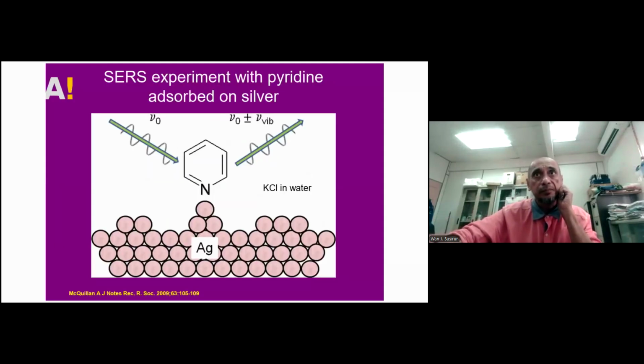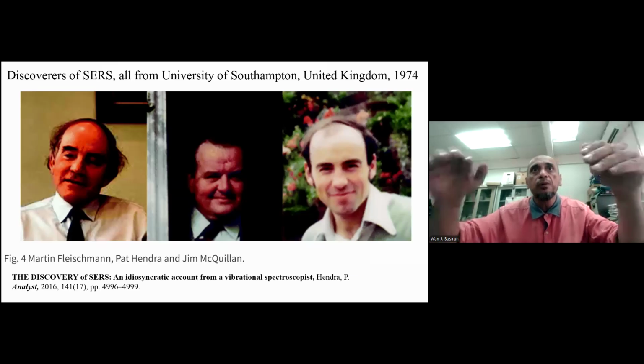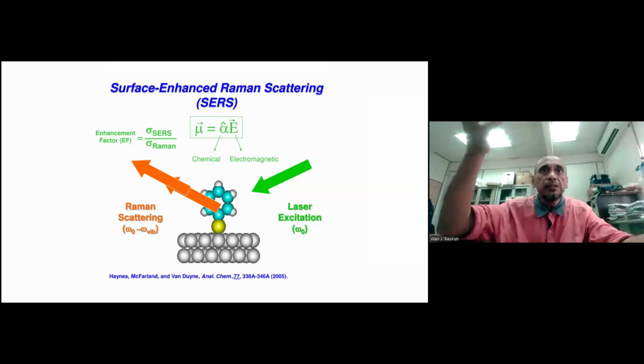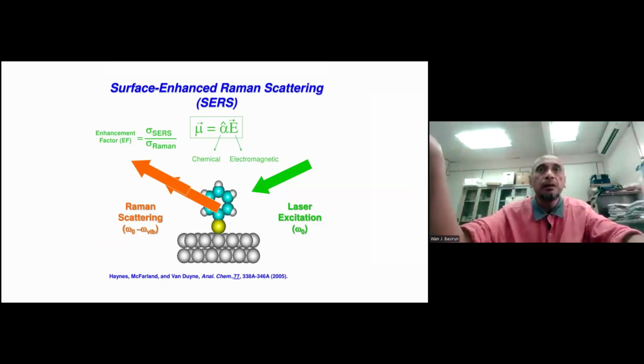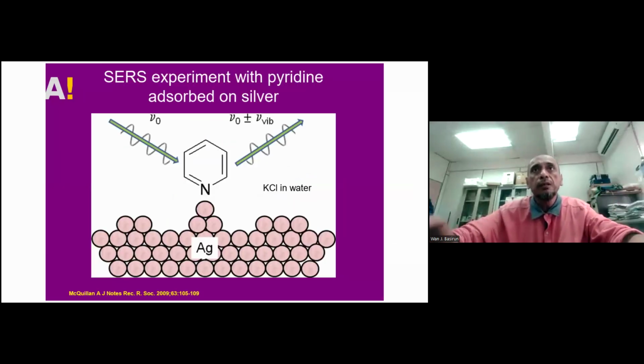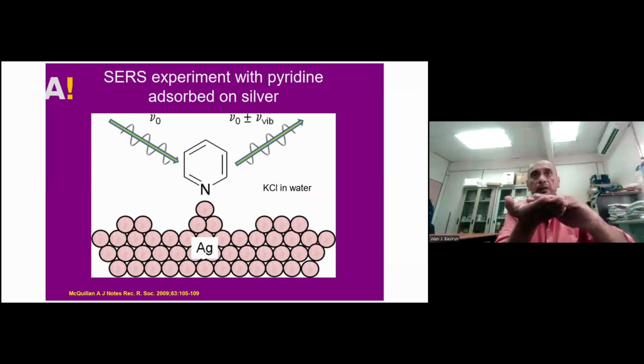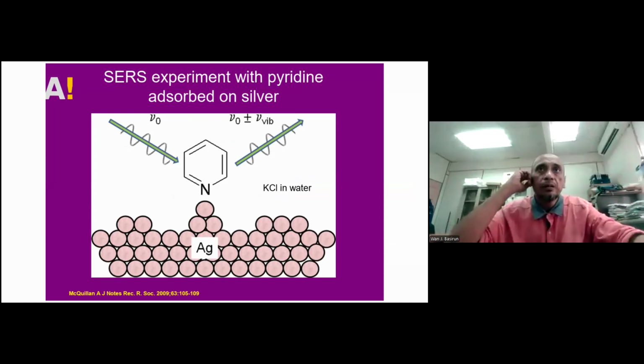Okay, so this is the same thing. You can also do this in water. For example, in this case, the pyridine was absorbed onto the silver surface just in air. They just dropped pyridine onto the silver surface, put it in the Raman spectroscopy, and you get the excitation. You can also do it in liquid. For example, if you have a glass container with a silver electrode on top, and then you drop in pyridine, which is a liquid, in KCl, you can still observe this effect, even though it is in a container which has KCl water inside. So that is a case of pyridine absorbed onto a silver metal surface.